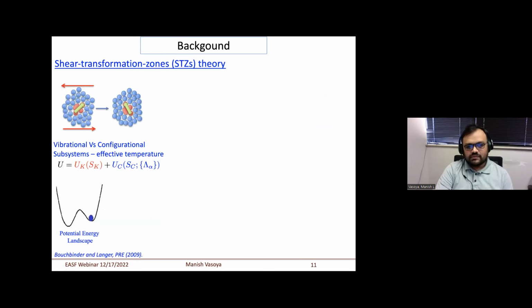Before I go further, let me introduce this theory. The crux is the decoupling of two thermodynamical systems: one called vibrational and the second called configurational. So the total energy can be divided into these two. Let me show you what vibrational versus configurational means. In the vibrational system, the atoms vibrate around their local positions, which induces the ordinary temperature. When you take the derivative of that energy with respect to the vibrational entropy S_k, it gives you the ordinary temperature.